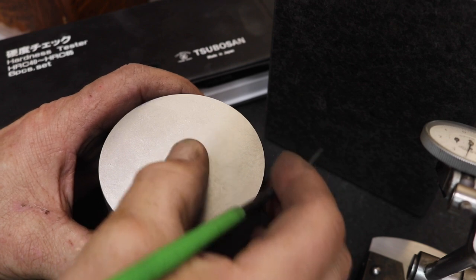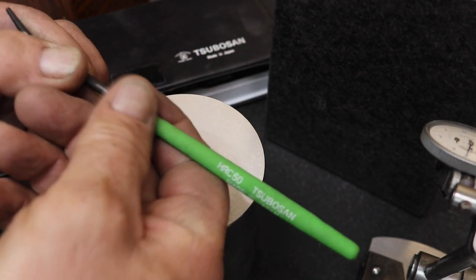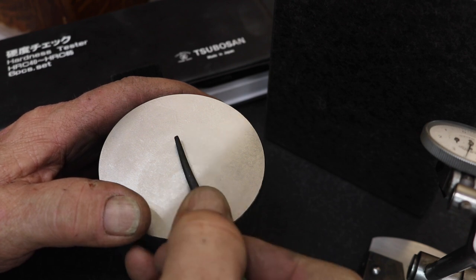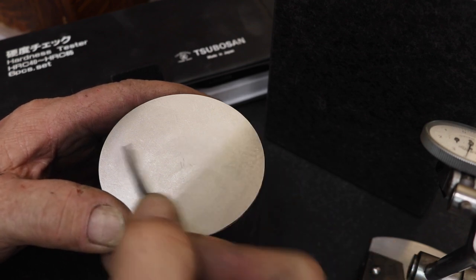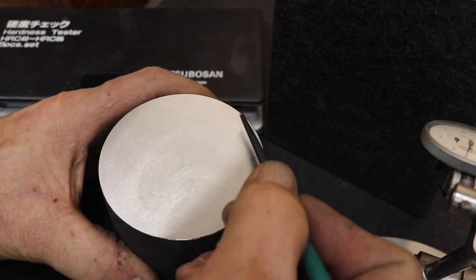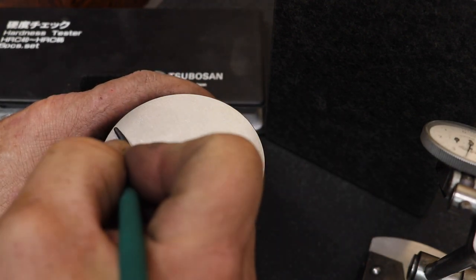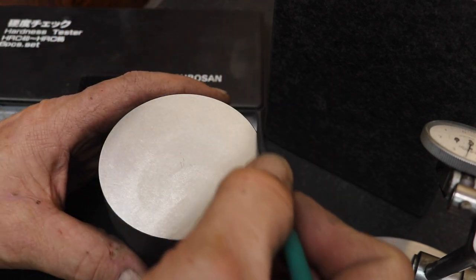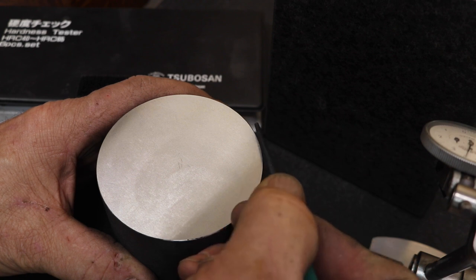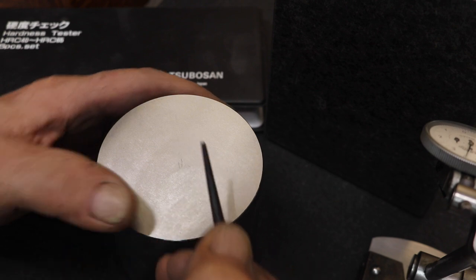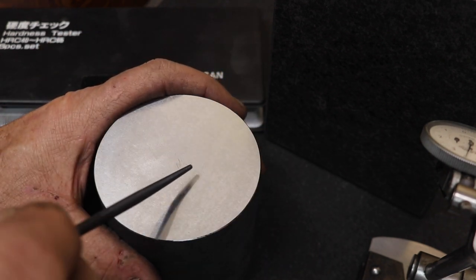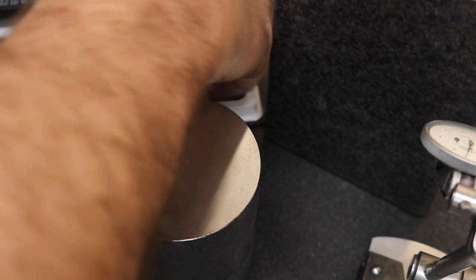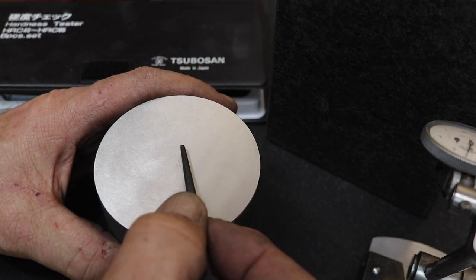I'll test this, now I got rid of all the scale and ground everything. And this is a 50. Let's see in the middle here, the middle should be the softest. And it's not grabbing, it's not grabbing anywhere. That's a good sign. Try 55. Now the edges could very easily be harder than in the middle. The center is where usually you'll have the softest as far as heat penetration goes. 55 is not grabbing at all out there. Barely, I'm at 55. So I would say I'm probably around 55 in the middle and harder at the edges.